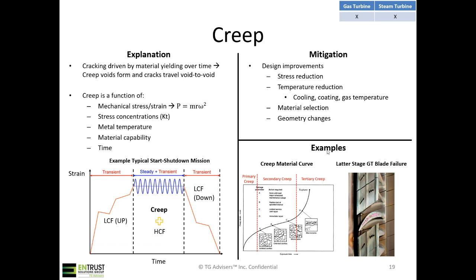In the bottom right corner, you'll see two pictures. The first one on the left is the typical creep material curve. There are 3 different parts of that curve. There's primary creep, which will occur during, we'll say, the first handful of hours in a part's life. And then there's the secondary phase. And you can see that's typically very linear and just slowly accumulates over time. And then once it hits a breaking point, you enter into tertiary creep, and that's where creep accumulates quite quickly and it leads to rupture.